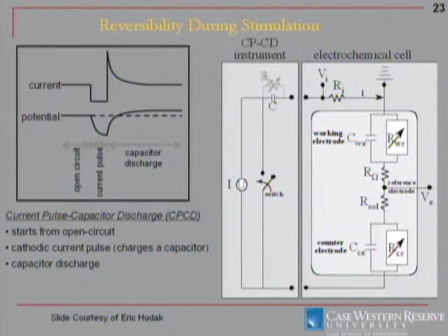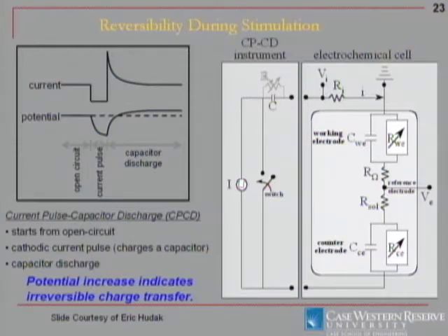In this case, it shows an example where the potential went more positive than it originally started at after the pulse. And that's an indication that the electrochemistry was not completely reversible. If it was reversible, it would have come right back to the same spot. So again, the potential increase indicates irreversible charge transfer.